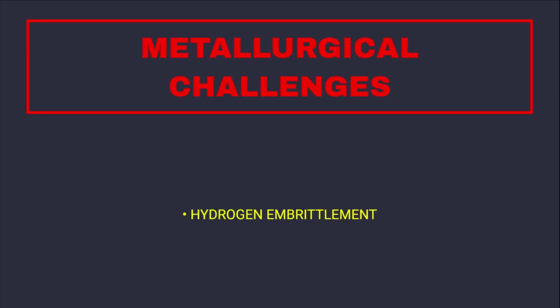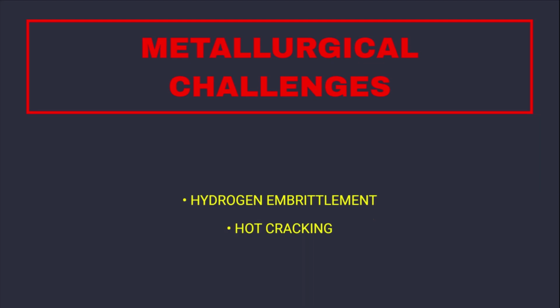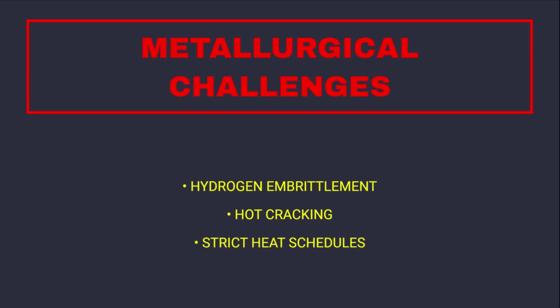It was highly susceptible to hydrogen embrittlement, requiring extremely strict control over atmospheric contamination during processing. Furthermore, the alloy exhibited a tendency toward hot cracking during welding and required precise heat treatment schedules to achieve the desired mechanical properties, often involving solution treating followed by aging. Failure to adhere to these narrow parameters resulted in immediate material rejection. Working with titanium alloys at this scale was a fabrication nightmare.